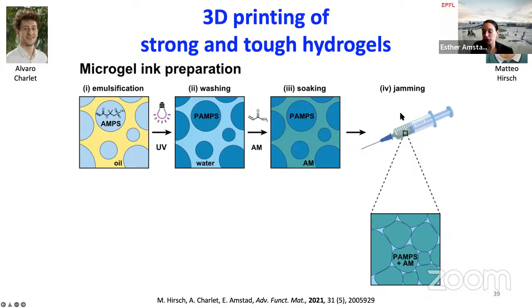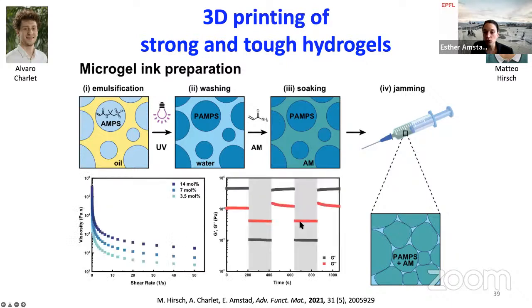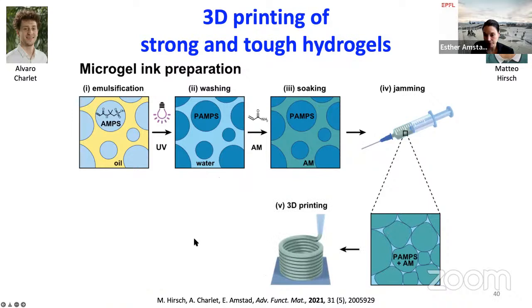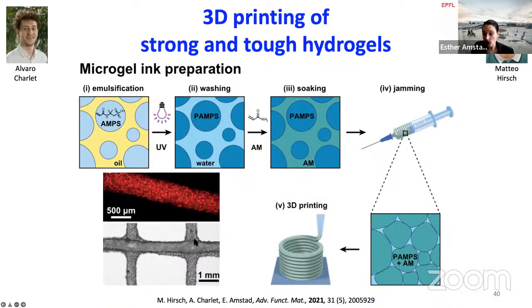So they actually printed these kinds of particles into macroscopic structures. Here is just rheology that shows that you have very fast shear recovery, which you need for 3D printing, and the shear thinning behavior. They 3D printed them. Of course, the granular structure was retained because the hydrogels don't break during this process.